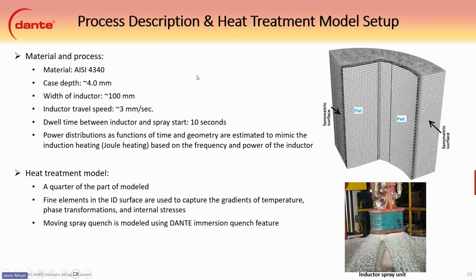So building the model again, this one was made of 4340 steel. It has a case depth of about 4 millimeters, and the width of the inductor is about 100 millimeters. You can see the inductor here at the bottom right. The inductor travel speed is about 3 millimeters per second up the shaft, as you see it on the part here. And then the dwell time between the inductor and the spray start is about 10 seconds. So it heats up for about 10 seconds before it starts to spray.